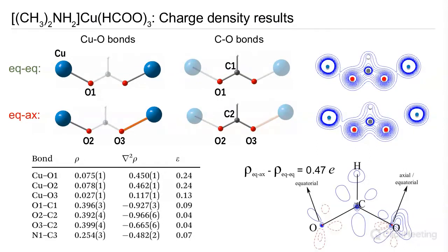So let's look at the results. If we look at the ligand first, the charge density results are shown on the top right here. On the top row is the equatorial configuration, which is observed to be antiferromagnetic, and on the bottom row is the equatorial-axial configuration, which is found to be ferromagnetic. What we see is that the charge density on the formate is remarkably similar, qualitatively at least, in both cases. So it seems like the formate is electronically the same in both scenarios. The difference really occurs just in the nature of the bond to the copper. What we see is essentially a more ionic character of the bonding to the axial copper on the right-hand side and on the bottom row.